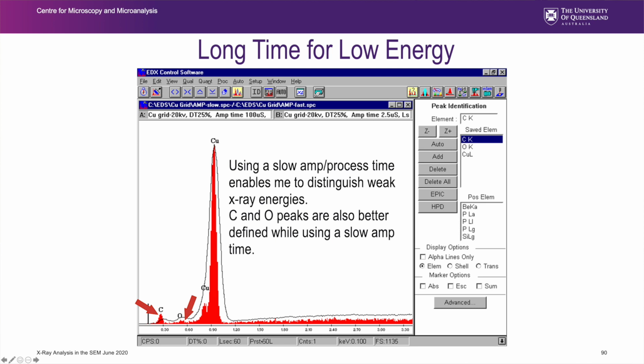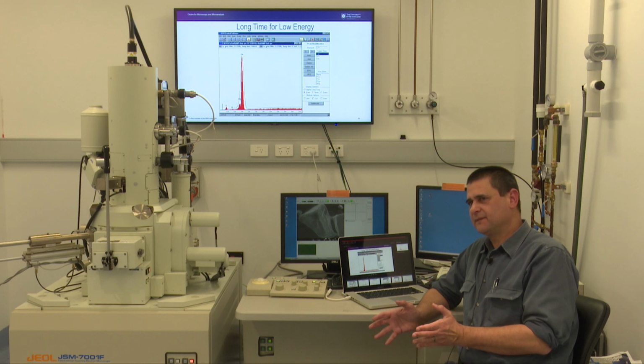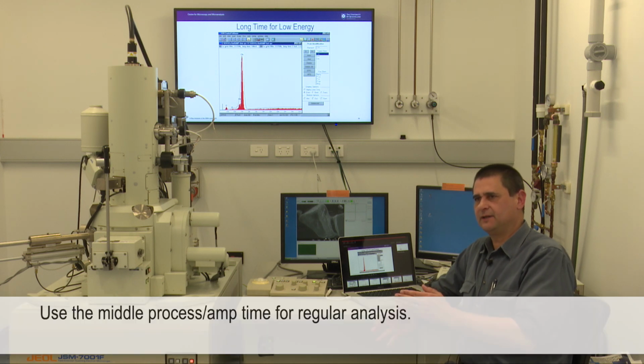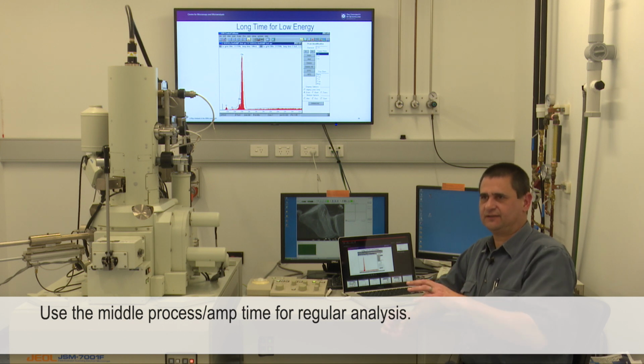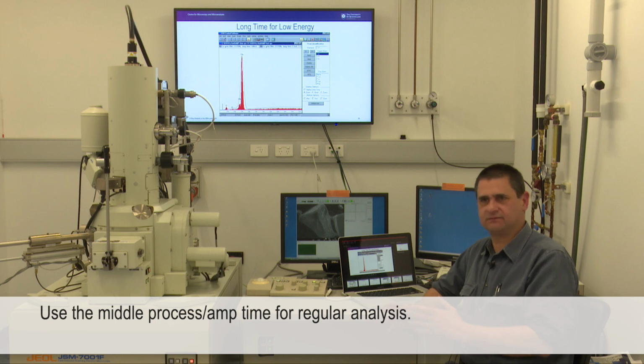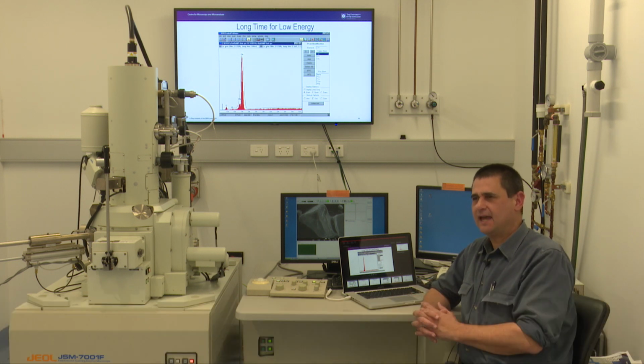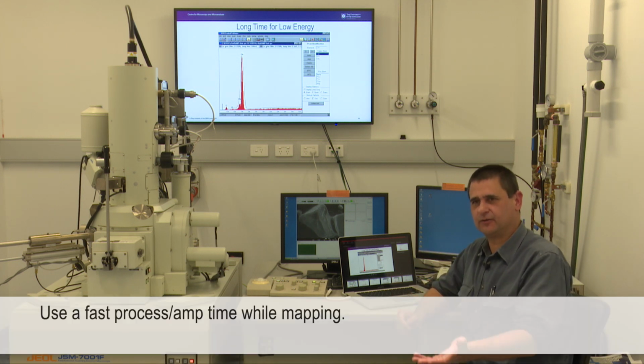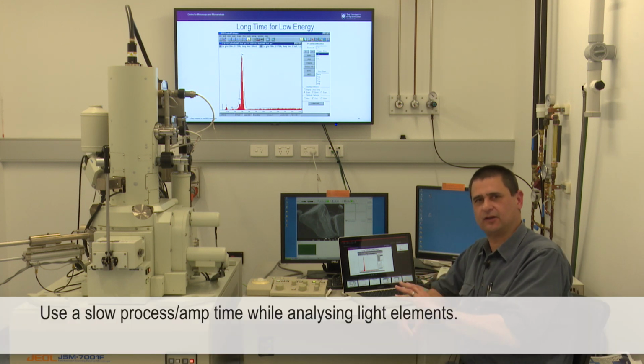So my advice to you is, if you don't know what you're doing, I usually leave the processor time somewhere in the middle. They tend to go from, say, 1 to 6. So I use 3 or 4 in the middle. That's a good does-everything processor time. However, if I want to map, I go a fast processor time, and if I want to do light elements, I do a slow processor time.